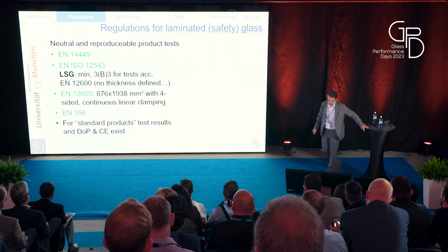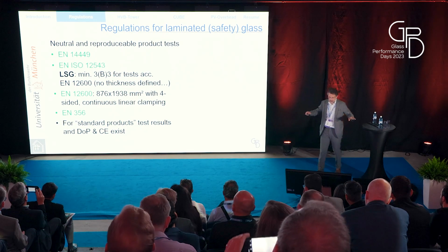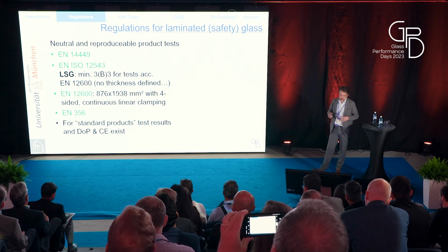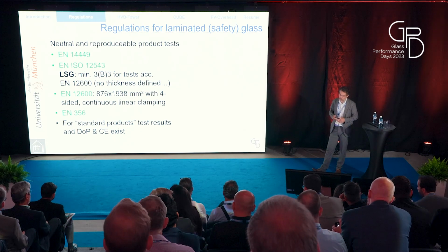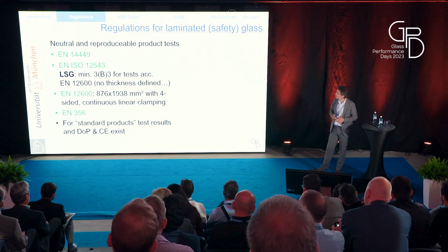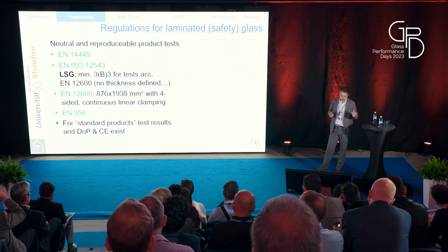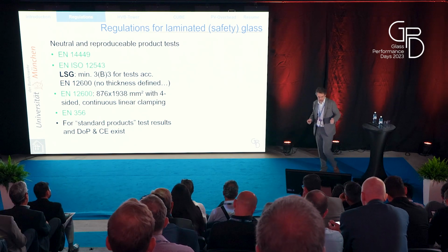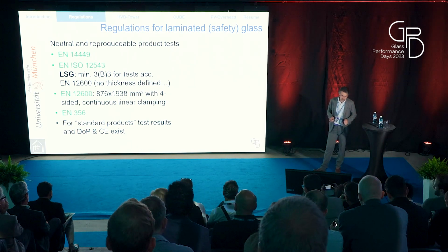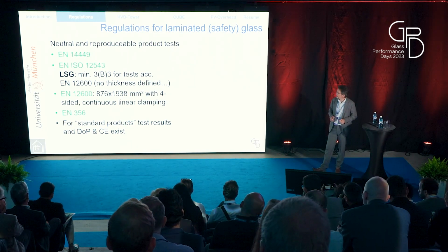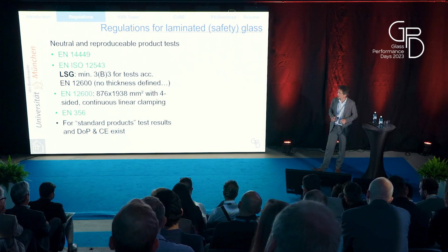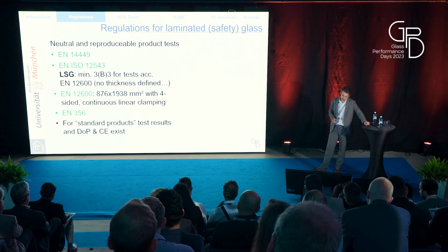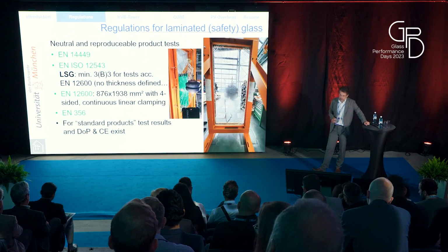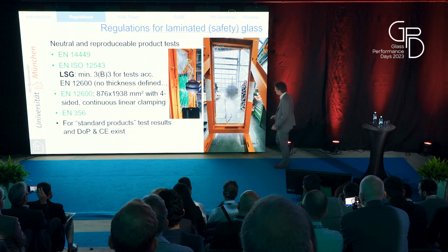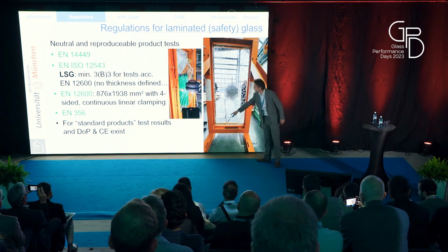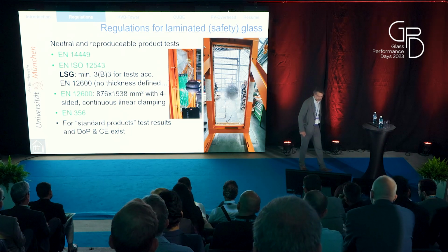The regulations on the European level for marketing of the products or for commercial distribution give a neutral, reproducible basis for doing tests. And there's one criterion for classifying a laminated glass as laminated safety glass. It has to reach minimum 3B3 for tests according to the DIN standard or the EN standard 12600. This is the pendulum test you do on glass of a certain size, framed on all 4 sides.